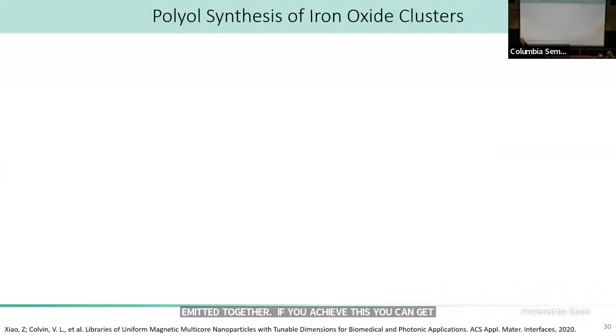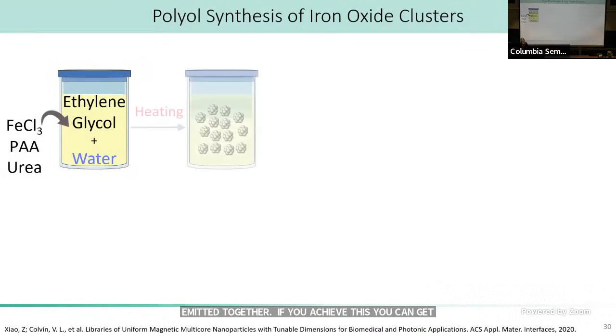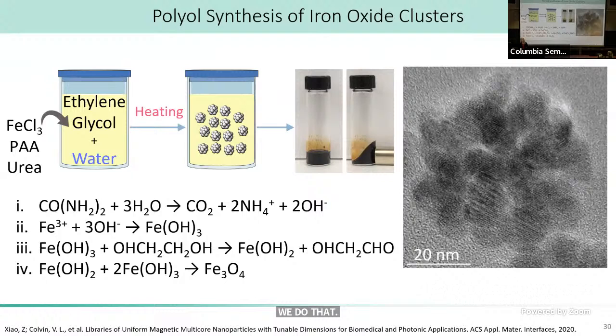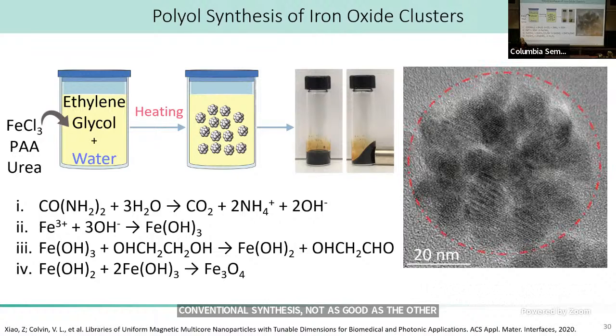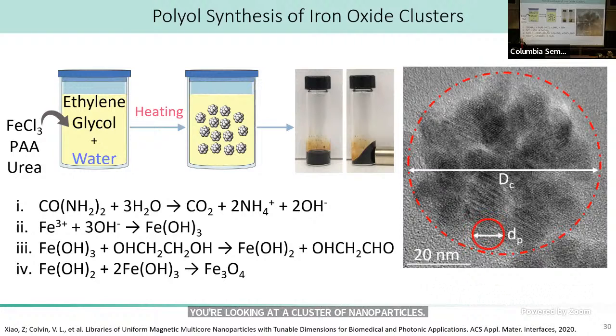So I'll tell you how we do that. This is going to go really fast because it's a lot of chemistry. So let me try to get to the final end goal. I'll stop with this picture because I think it's the one you need to see. We produce these materials using a pretty conventional synthesis, actually not as good as some of our other syntheses of nanoparticles because we intentionally aggregate the particles together. So what you're looking at here is a cluster of nanoparticles. They have an overall dimension, but they also have a small primary dimension. And they are 50% porous. So there's a lot of internal surface area because they're not perfectly condensed.